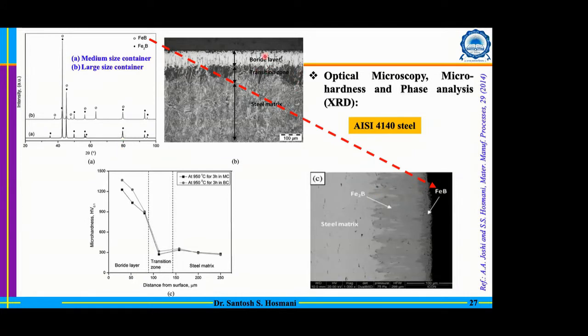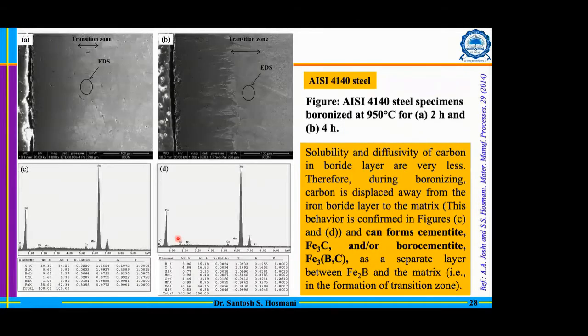And there is an interesting thing, a transition zone, which has formed between the boride layer and the steel matrix. If you look at the micro-hardness profile, the transition region has a lower hardness, and that will happen at a later stage of the boronizing process. We were very curious to understand what exactly this transition zone is, and we did some investigation. We realized that this transition region is basically associated with the enriched elements which are rejected by the boride.